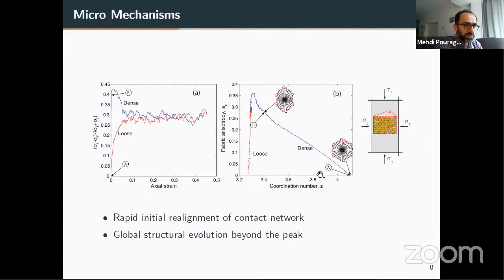The assembly is losing so many contacts. The coordination number is decreasing going from A to B, and the anisotropy is increasing because the contacts are not lost equally along different directions. We see that the contact distribution changes. So we have a very rapid initial realignment of the contact network with basically negligible strain. And then after the peak is where we see large strains taking place, which is in this zone.